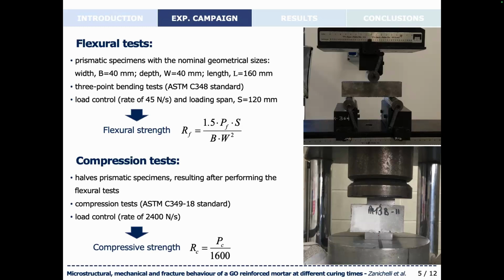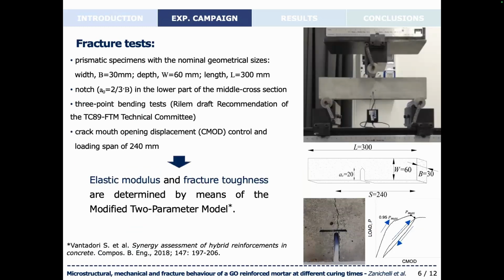Then the 6 half prismatic specimens resulting after performing the flexural tests were subjected to compression tests in order to determine the compressive strength. And moreover, 4 prismatic specimens with the nominal geometrical sizes shown here at the top, with a notch in the lower part of the middle cross section, have been subjected to 3-point bending tests in order to determine both the elastic modulus and the fracture toughness by means of the modified 2-parameter model. Such a model, proposed by Vantadori and co-workers, allows us to take into account the possible crack deflection during the stable crack propagation phase, even in the case of a remote pure mode I loading applied to the specimen.